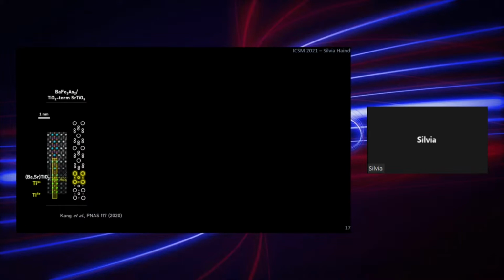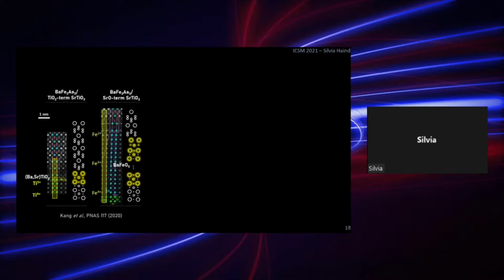The situation is similar in the case of the strontium terminated STO, where we have barium iron 2 arsenic 2 grown on top of this strontium oxide terminated STO. Here, however, the interface layer is much larger. So we have here a barium iron oxide interface layer, and it is much thicker.